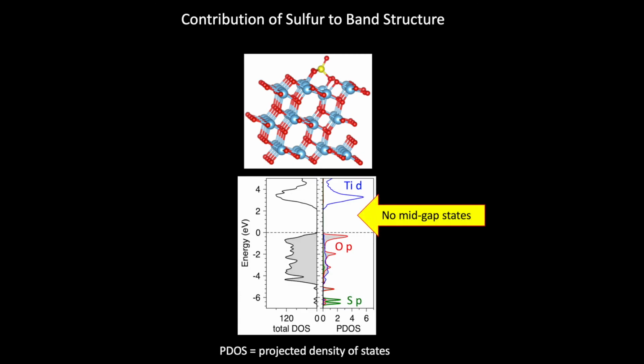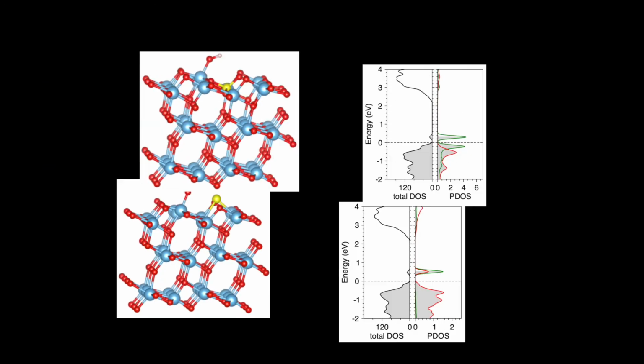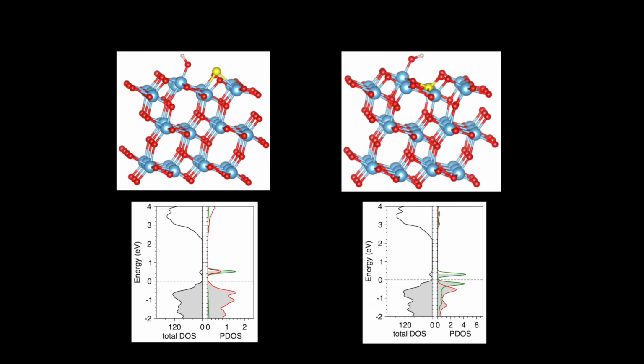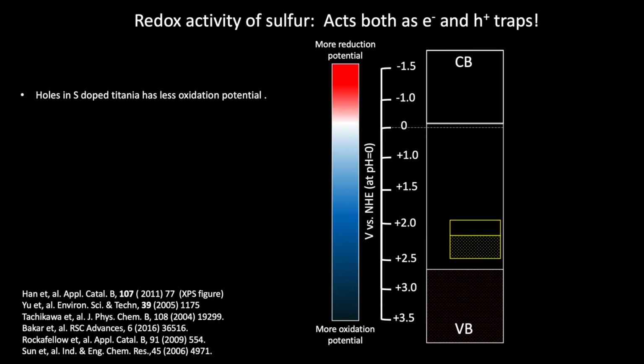Our band diagram calculation results back up the experimental findings, showing that sulfate-like structure is not creating any electronic states in the band gap. But sulfur sitting on titanium or oxygen sites in an oxygen-rich condition results in creation of partially filled states above the valence band maximum. There is experimental evidence in the literature showing that holes created under UV radiation in sulfated titania have lower oxidation potential because of hole entrapment in sulfur states.